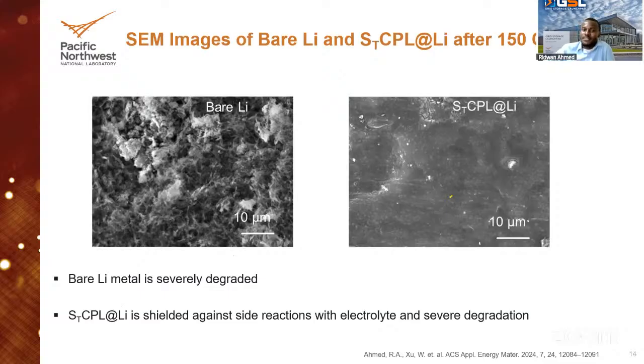So after cycling our cells in the lab, we also do what we call post-mortem analysis. Like we try to check all those electrodes to see what's happening to them. So one of the things we do, especially for the anode part, which is the lithium, is we just take the SEM images after cycling to see what happens.